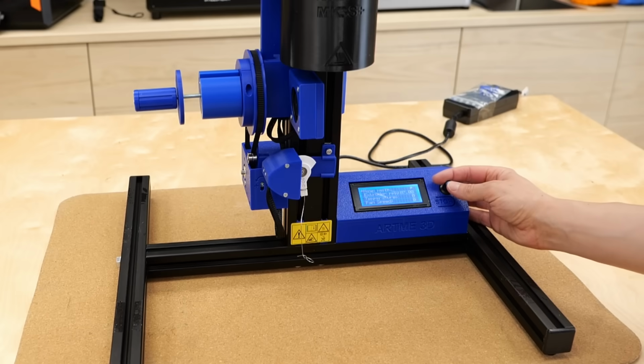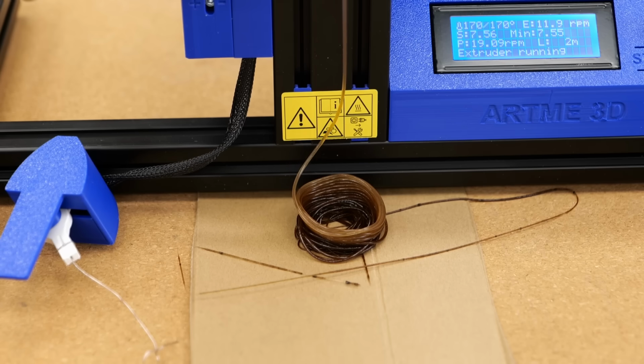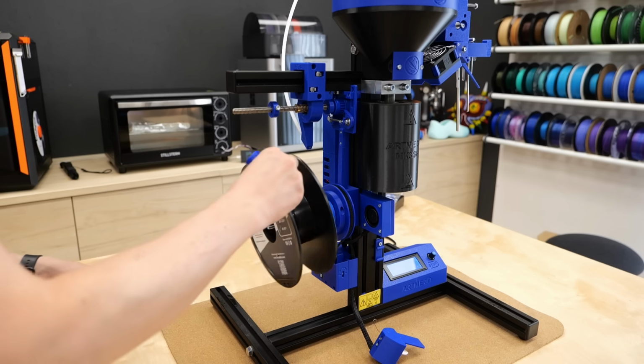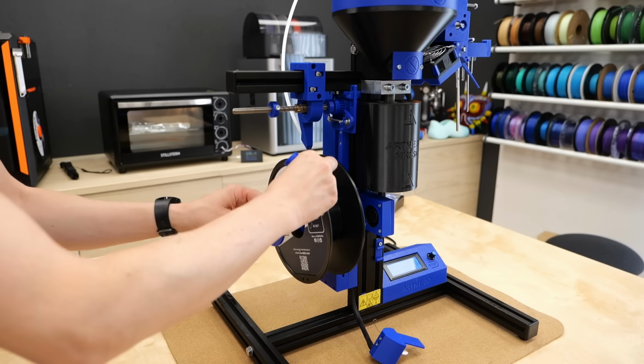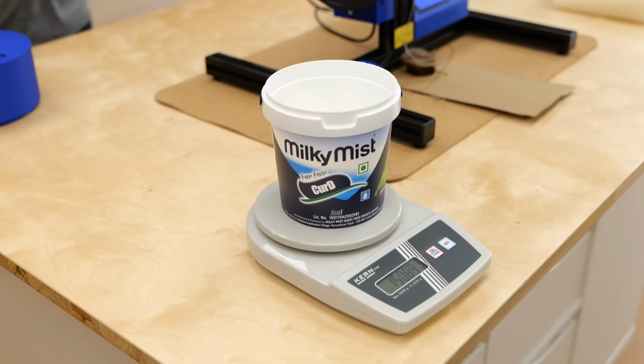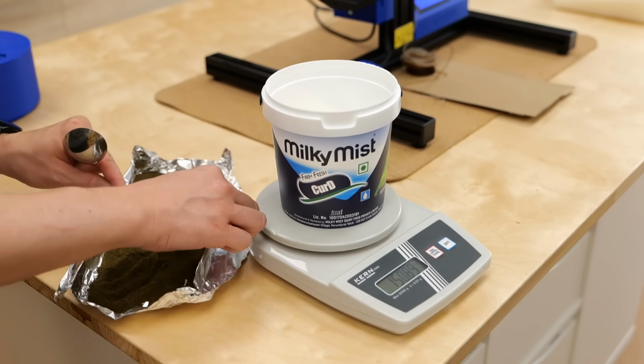Before I could extrude the cow dung filled filament, I had to preheat the unit to 170 degrees Celsius, and once it reached that temperature, I purged out the old material that was still in the barrel. While it was preheating, I first installed an empty spool on the winder, and then got my poop powder out of the oven and prepared the first mix.